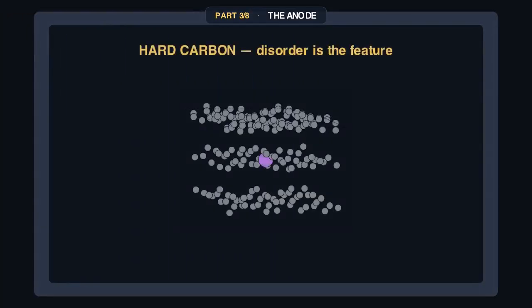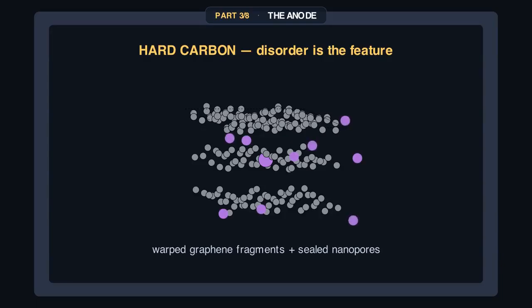So we throw out the neat lattice and reach for its messy cousin, hard carbon. Not a defect, a feature. Instead of tidy stacks, it's a chaos of warped, disordered graphene fragments riddled with tiny sealed nanopores. And that mess is the whole point. Sodium can't orderly stack in a crystal, but it can hide in this jumble, stick to all those defect edges, and pack into the pores. Where the ordered lattice rejected sodium, the disordered one welcomes it.